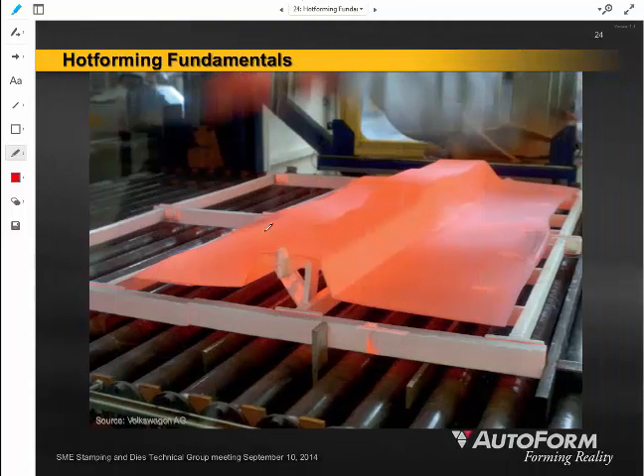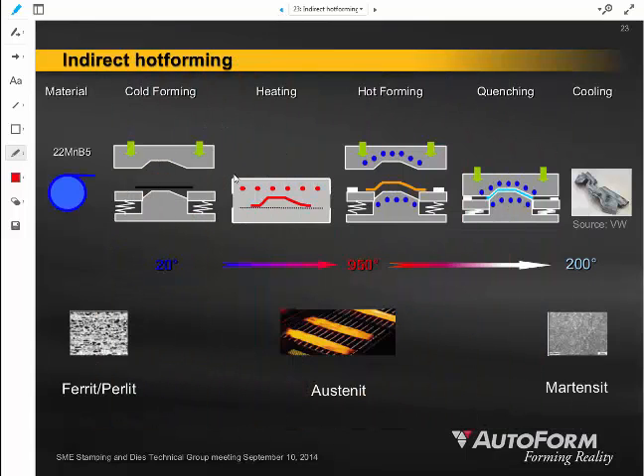Here's an example. This is a photo of a part in that indirect hot forming. You can see that this part is coming out of the furnace red hot, and it already has some product shape applied to it. So in this case, this was indirect hot forming. They did some room temperature deformation of the part at ambient or room temperature. Then it went through the furnace to get heated up to the appropriate temperature, and then hot formed and additionally quenched and cooled in that environment. And that gives you perhaps the ability to form even more sophisticated, more complicated shapes than we would have achieved if we just did it in one hit.